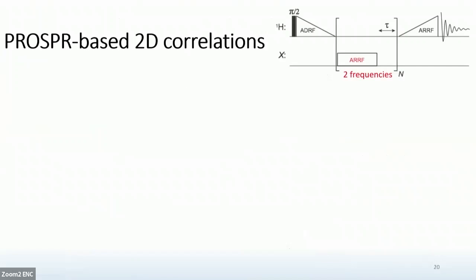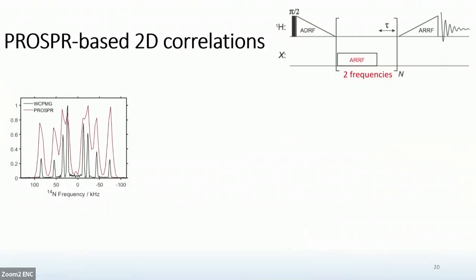And finally, I would like to present a new idea that we had. So if we go back to the single crystals, this is the N14 single crystal that we grew. And initially, we weren't sure if they're single crystals or not. And then we wanted to be able to correlate each satellite transition to its symmetric satellite transition. So we came up with this. This is essentially the same sequence, PROSPR, but at each CP step, you irradiate at 2 frequencies at the same time. One frequency is kept constant, and then the other frequency we sweep in the same way that we do with a regular PROSPR experiment.